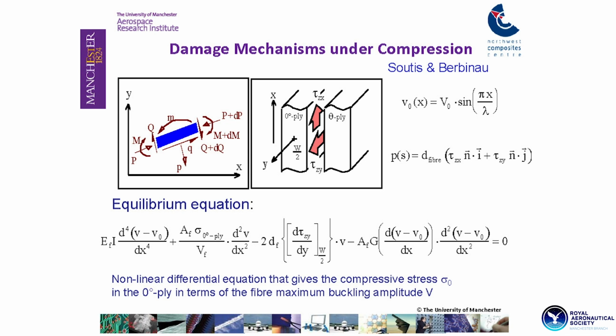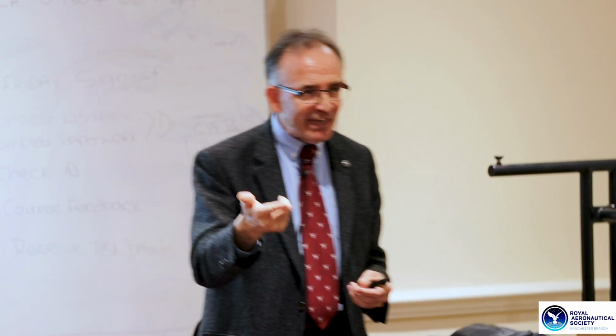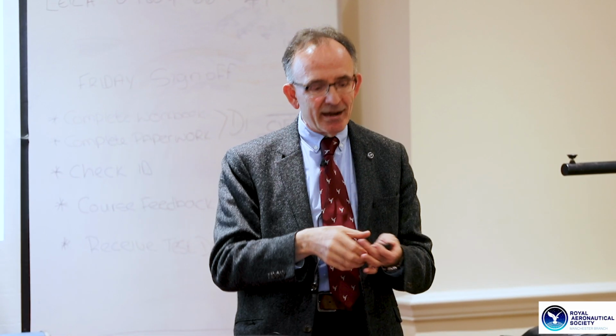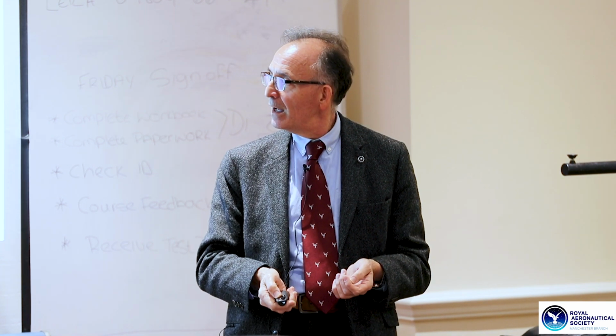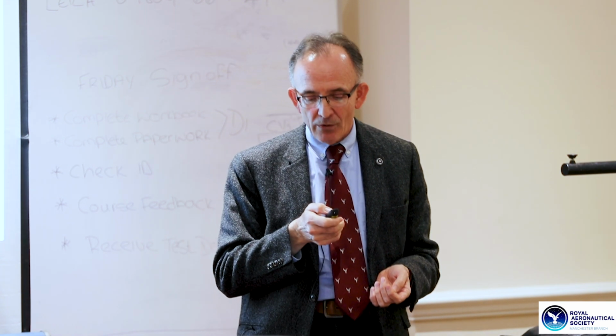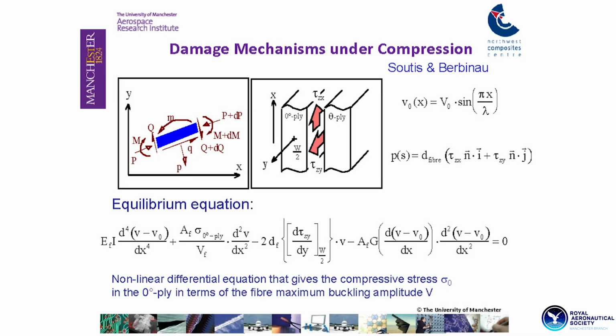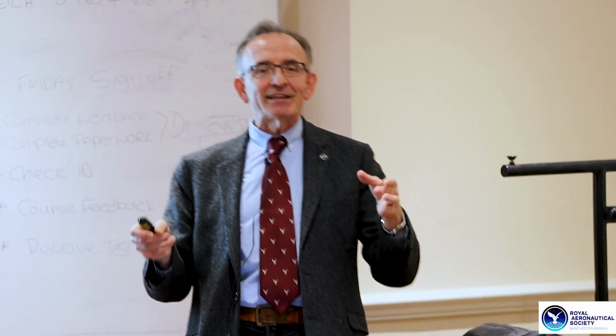So the challenge that we have is to identify non-destructively that damage that happens inside, identify what's the critical length, and predict or estimate when that laminate is going to ultimately fail. And here is one of my models that takes into account initial imperfections, the properties of the fiber volume fraction, and tries to calculate, by solving this fourth order differential equation, the critical stress at which fiber instability will take place, accounting for interlaminar shear stresses that develop at the free edge.